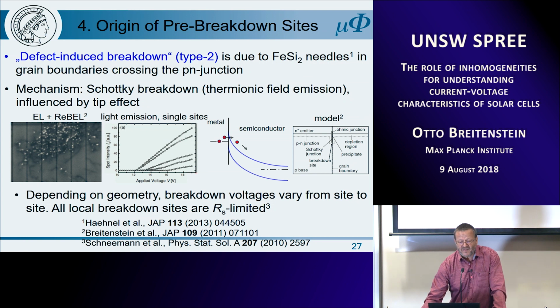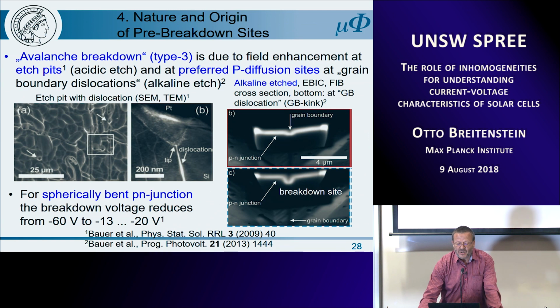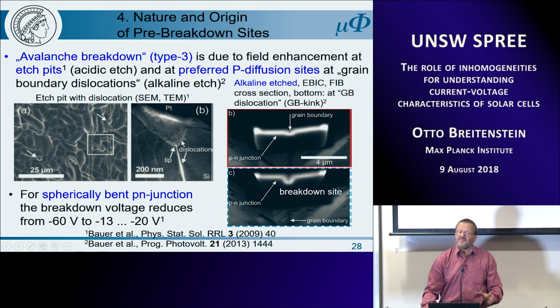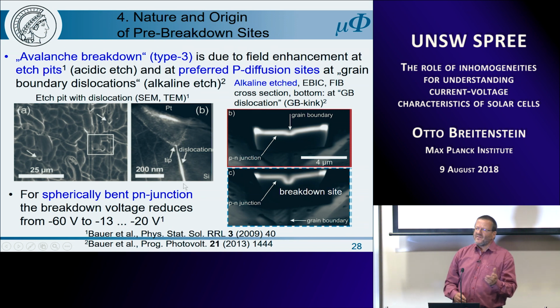Okay, now let's come to the third type, which is avalanche breakdown. We have found in multicrystalline material, which is acidic etched, that in these positions of breakdown, we find these funnel-shaped etch pits. This is a cross-section through an etch pit together with a dislocation. It's a special type of dislocation. You have to know that this etching procedure is actually optimized not to lead to preferred defect etching. Nevertheless, some special types of defects lead to etch pits.